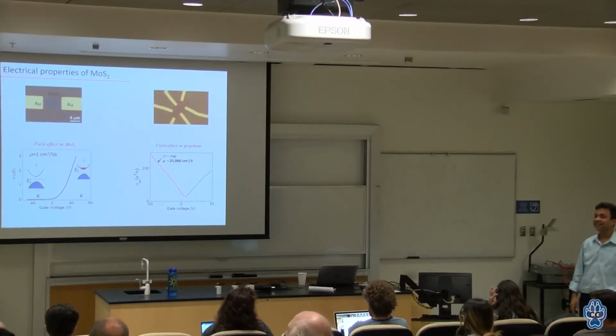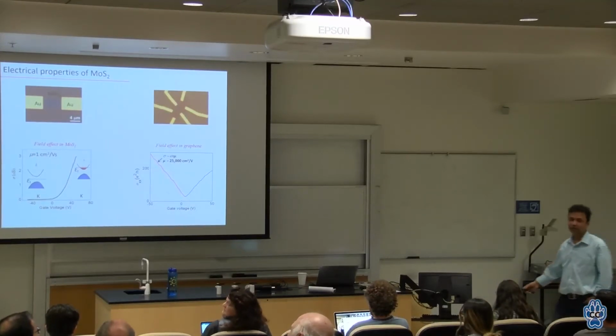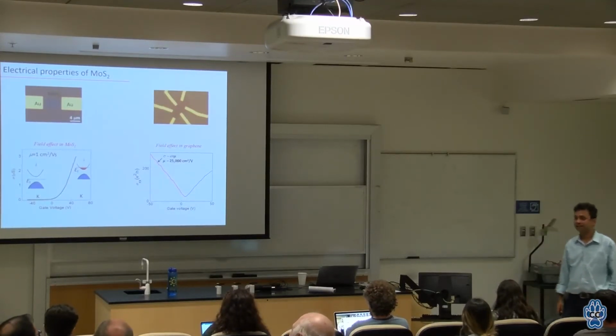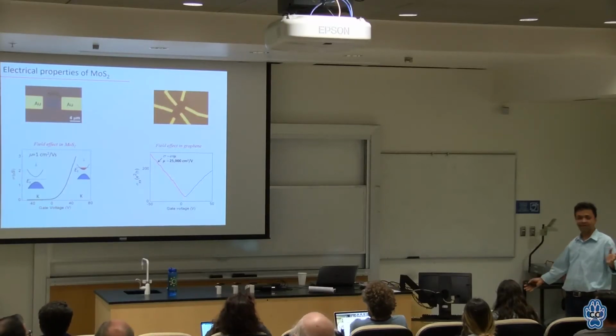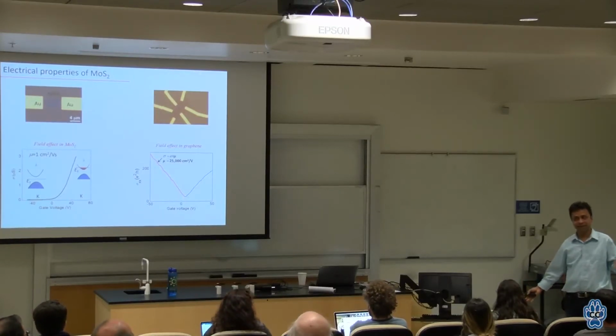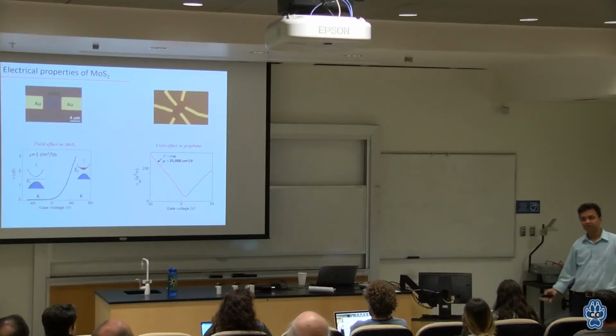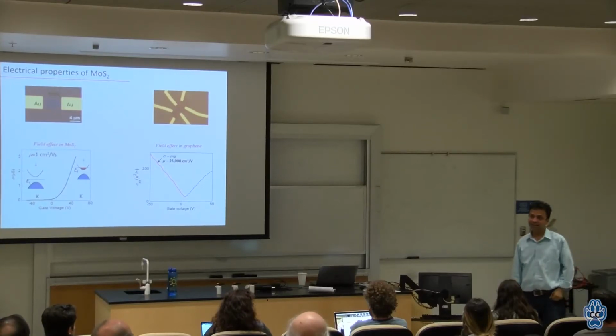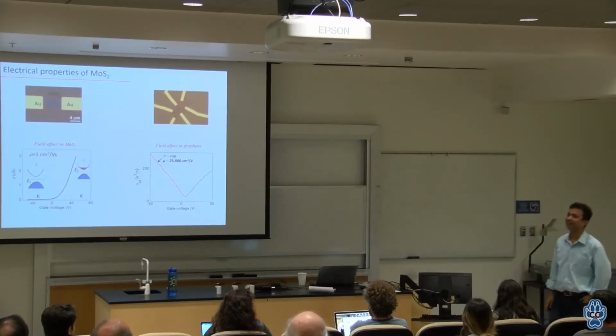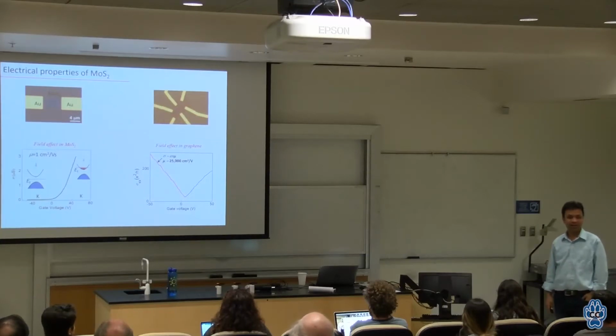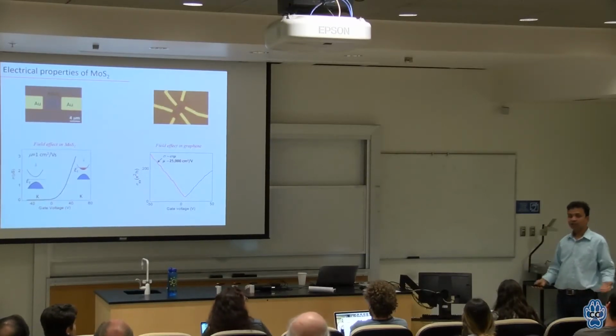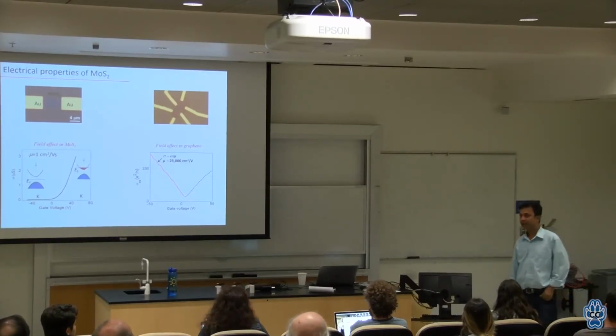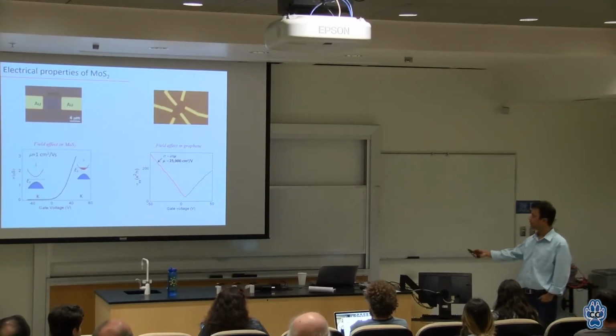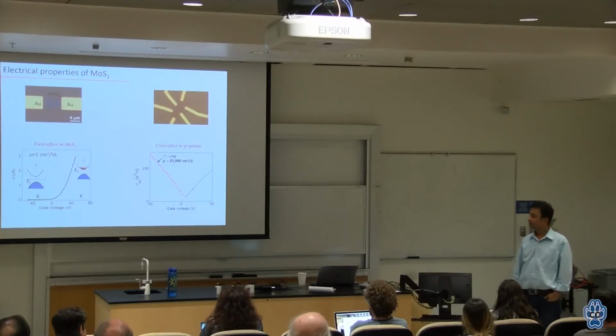Isn't it true your mobility is only 1 centimeter squared per volt per second? People have gone to 100 now. 100 centimeter squared per volt per second. I think recently they have even seen quantum Hall effect behavior in MoS2. So people are improving, but it's slow. It's only 8 years now, so people are working on figuring it out. One of the reasons is that MoS2 has lots of defects in it too. It's very hard to make high quality compared to graphene.